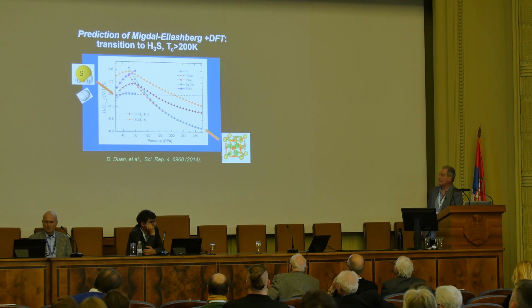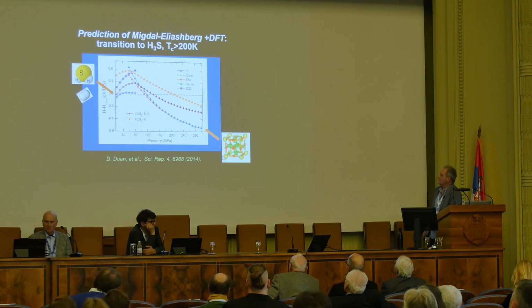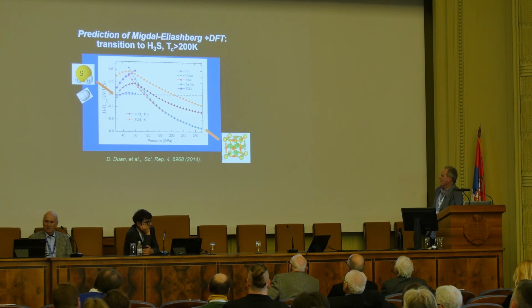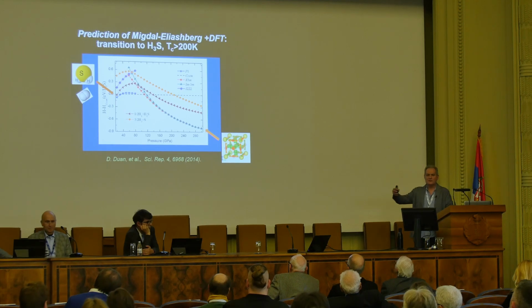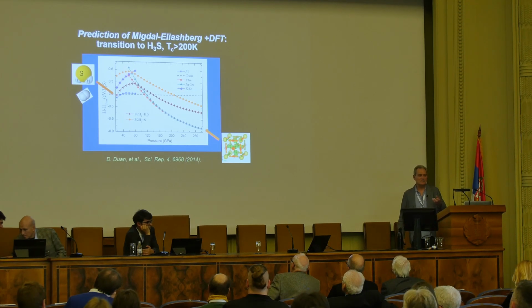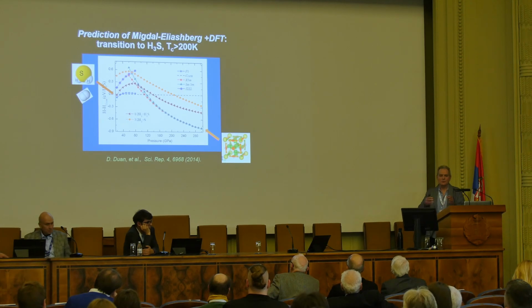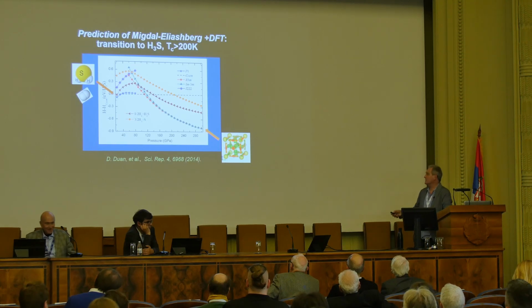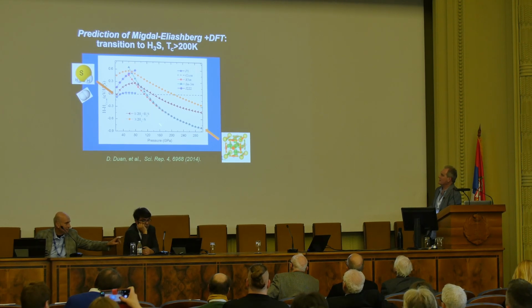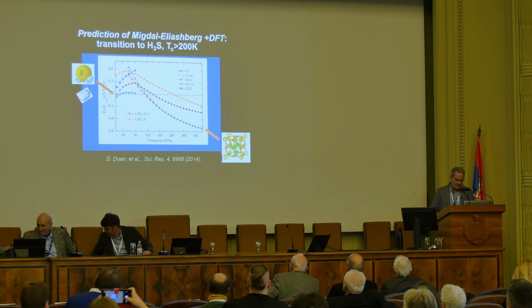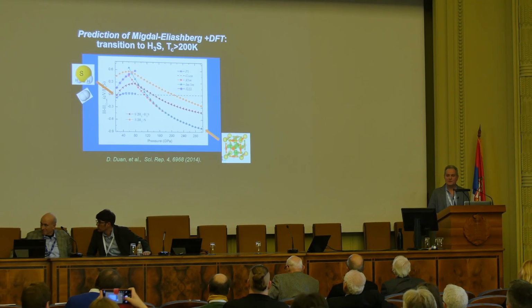This is one of the first great successes of computational superconductivity. The paper from Duan et al., where they not only predicted that the critical temperature would come out right at 100 gigapascals, but they predicted the sequence of structural transitions. Hydrogen sulfide goes in as a gas at low pressures, and then it solidifies. It goes into one structure. Then there's a structural transition to the eventual superconducting structure here. All that came out of this density functional theory plus Eliashberg theory calculations.